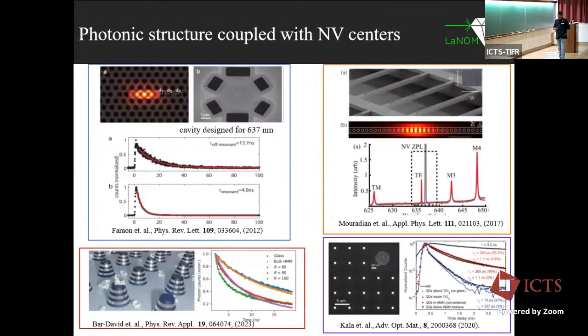And this is a very active area where you create photonic crystal cavities, where you have a periodic arrangement of dielectric constants. You can see there is a cavity here, and you have an NV center trapped there. And you do an emission measurement, a decay rate measurement. In the reference sample, you have around 13.7 nanoseconds. But when you do the experiment in the cavity, you get around 4 nanoseconds. So by trapping the NV center in this kind of cavity structure, you can speed up the emission process.